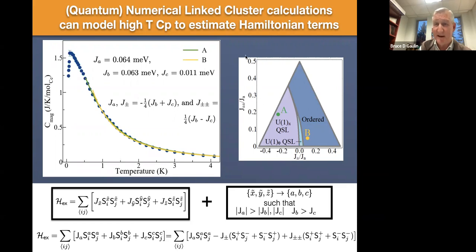Okay, and we've got again ratios of the 3 exchange constants, but they're now related to JA, JB, and JC. And again, you get quantum disordered states for one part of the phase diagram, and then more conventional ordered states for the other part of the phase diagram. Okay, so you can tell which parts of these phase diagrams you're in, but because you've lost the information about which exchange constant is which, if you get a quantum spin liquid state, say at this position A, you don't know if it's dominated by the octupolar interactions or by the dipolar interactions. And the same is true with the ordered states.